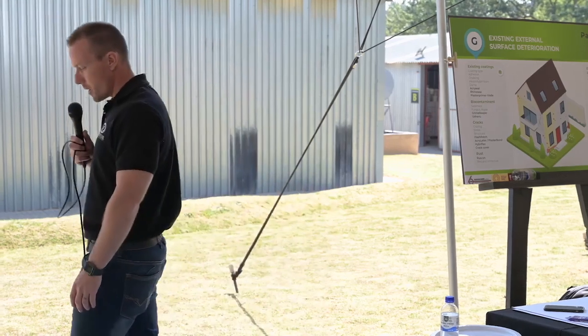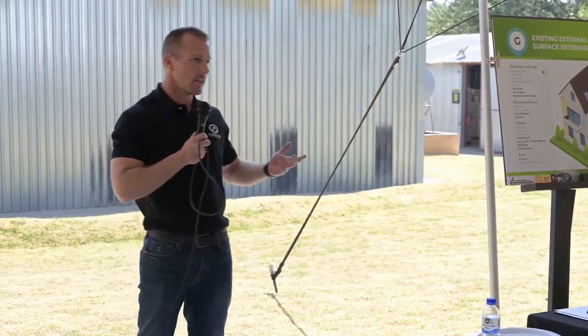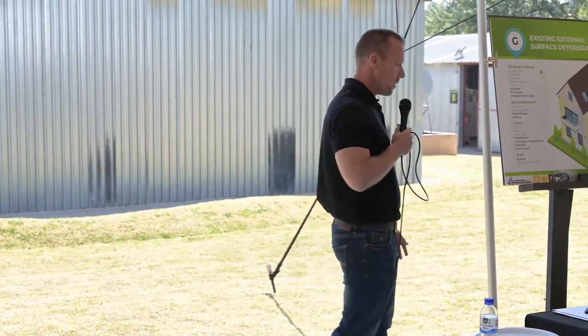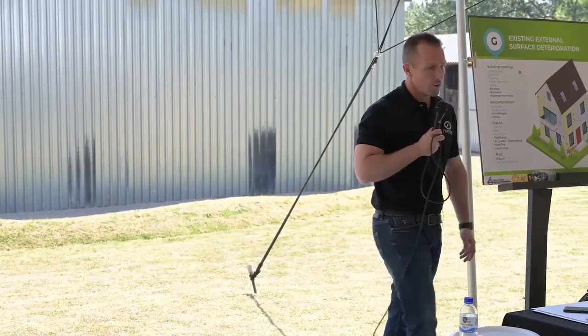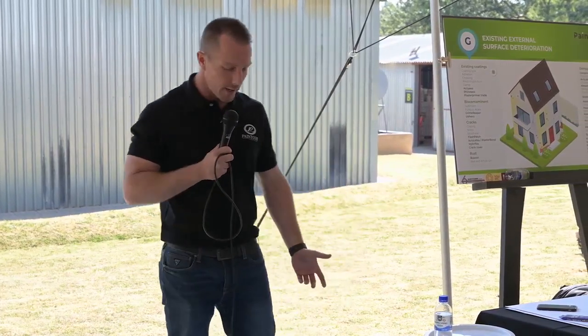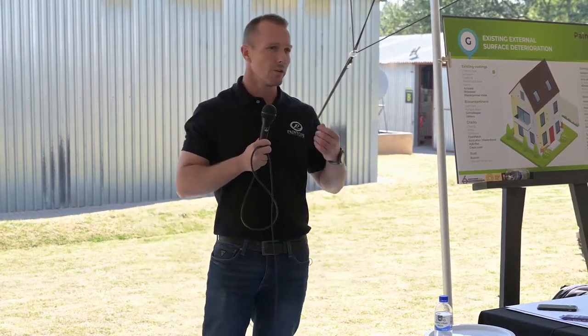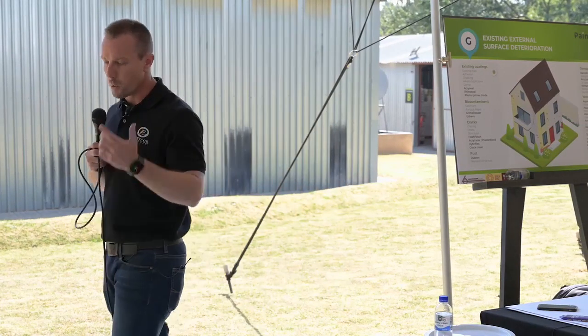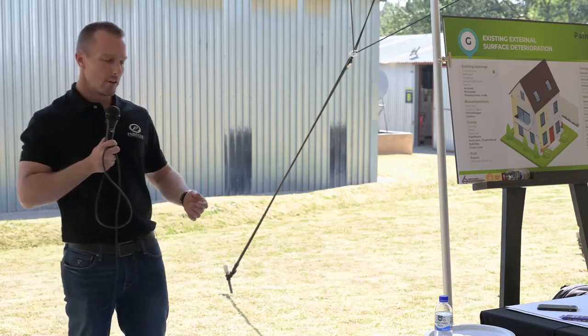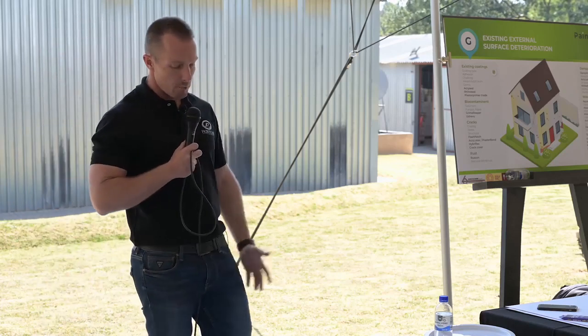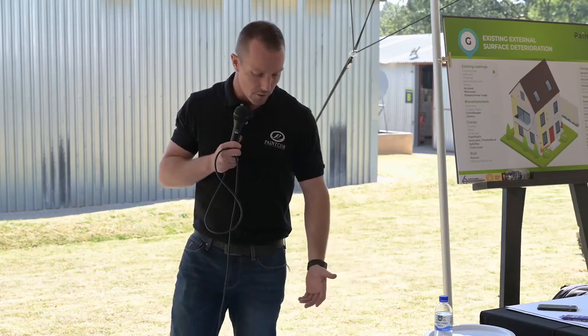Ordinarily, this would happen on an existing structure as a result of cracks. Now, cracks, ladies and gents, are the number one cause of paint failures in our industry. It's cracks and more cracks. It's cracks that will cause these types of failures, but it's also cracks that are going to expose shortcomings in your waterproofing and damp-proofing work. It's cracks that are going to lead to the delamination of paint and the general deterioration of a painted surface.